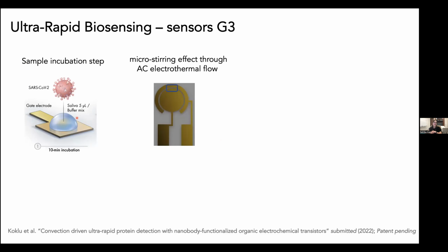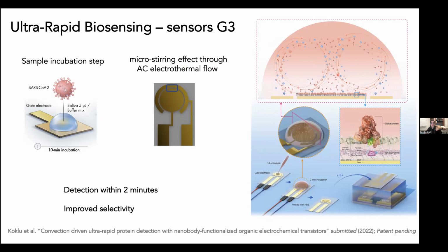So one way to mitigate that is to do the mixing externally, making a new gate electrode design, which allows us to generate an AC electrothermal flow in the sample mixture. This AC field is causing a micro-stirring effect in the solution that allows the target proteins to come and bind to the surface. They are captured and some non-specific ones are thrown out. This lowered the detection time, which was the sensor's speed-limiting step, from 10 minutes to 2 minutes, and it also improved the selectivity of the sensors that we built.